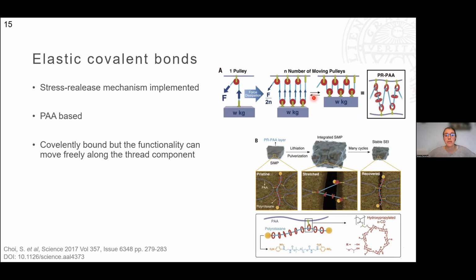My last example is this one, where they used elastic covalent bonds. They have also based their binder on PAA here and focused a lot on the mechanism of the binder during the expansion of the silicon particles. The binder in the paper was developed based on this mechanism of the pulleys, which I think is quite well explained in this figure. By multiplying pulleys that are attached, using multiple of them, they can move the rope and use less force to either lift something or, in our case, pull something together.